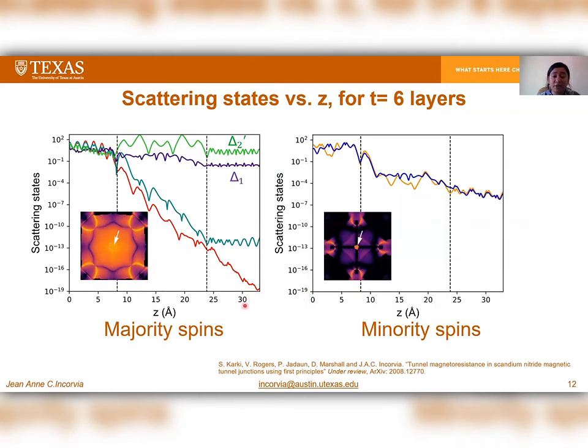Further on, we looked into the scattering states versus Z for several k points for different layers. This is an example of a 6-layer system. On the left are the majority spins, and on the right are the minority spins. The in-between layer is the scandium nitride layer sandwiched between Fe left and Fe right. Fe left is from 0 to 8, and Fe right is from 24 to 32. We see on the majority channel that there are delta 1 and delta 2 prime, whereas when we look at the scattering states for the minority spins, we see that these get filtered out. This is an essentially important point, as we can validate that scandium nitride can do a symmetry-resolved filtering mechanism for its majority and minority spins.